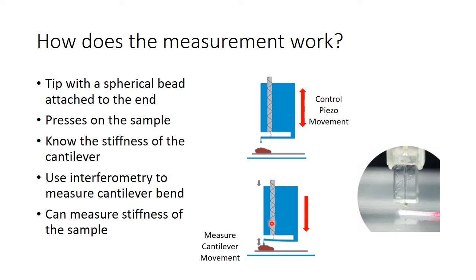Now this portion here is an interferometer that can very accurately measure the position of this cantilever. And so as it bends, we can measure that change in its bending. And by doing this and knowing the stiffness of this cantilever, we can then extract the modulus or the stiffness of the sample. This image over here on the right is an image of the tips that we use. They are made out of glass, and the working portion of the tip is right here at the end, which is contacting the sample.